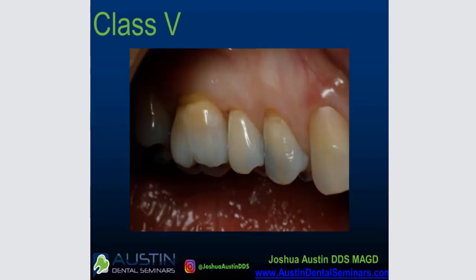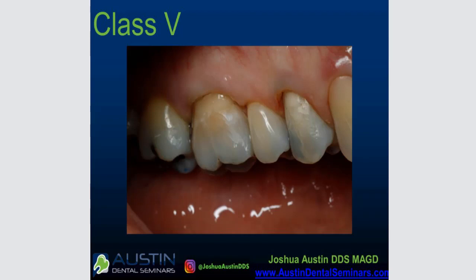Here's a case. We have 2 class 5s here, and kind of one developing on the maxillary first molar. We have a class 5 that's 1.5 millimeters deep, probably about 1/2 millimeter on the second premolar, and on the first premolar we have one 1.5 millimeters deep, and those are the points at which you need to start thinking about restoring these, when they get to 1.5 millimeters. These are a couple that have been restored with 2 different restorative materials that I'm going to show you later, and these work very well.